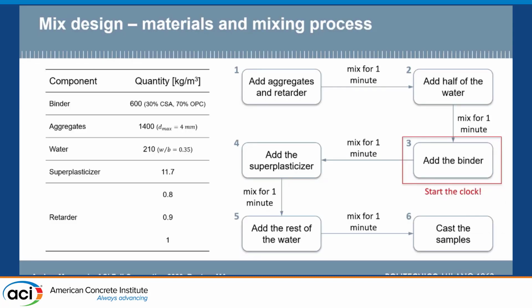This is the mix design adopted during the experimentation. So we have 600 kg per cubic meter of binder, made of 30% CSA and 70% Portland. 1400 kg per cubic meter of aggregates, mainly sand with a maximum diameter of 4 millimeter. In this case, the aggregates are different compared to the real scale application. We have just adopted a new size distribution for the tests. Water binder ratio is 0.35, with superplasticizer, and then three quantities of retarders.